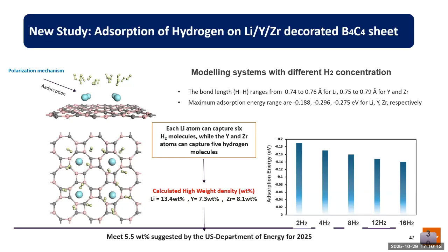In this decorated boron carbide, the bond length of hydrogen to hydrogen ranges from 0.74 to 0.76, and 0.75 to 0.79 for yttrium and zirconium. And the maximum adsorption energy is minus 0.188, minus 0.296, and minus 0.275 eV for lithium, yttrium, and zirconium.